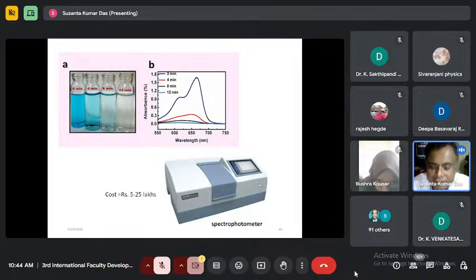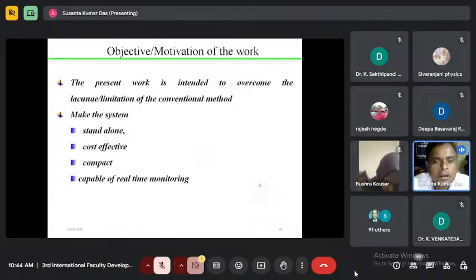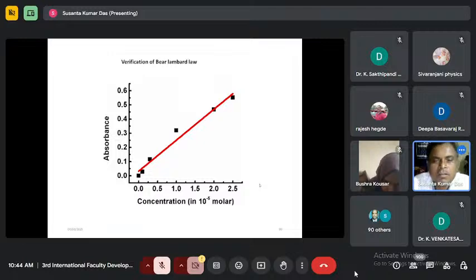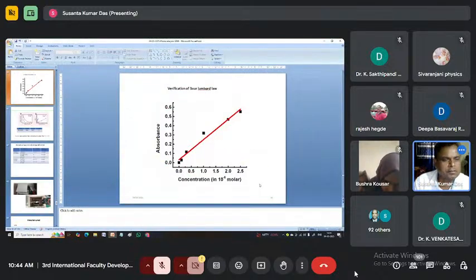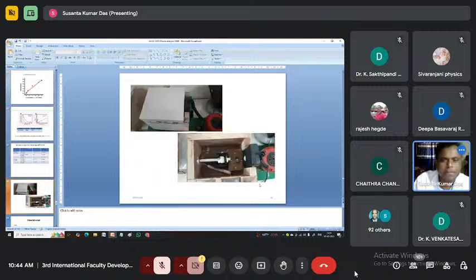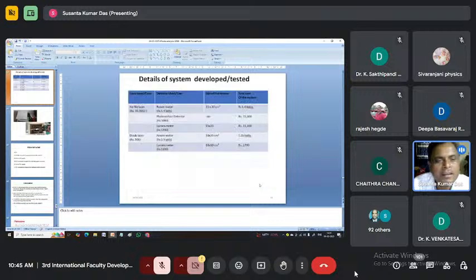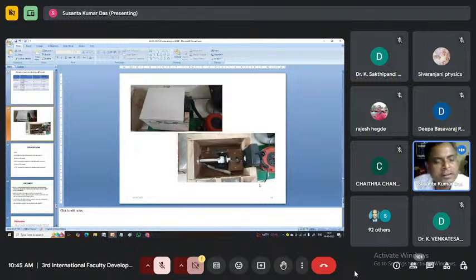So I tried a very simple setup, and the setup I'll show you. This is the setup actually. On one side I placed a lux meter, on the other side the laser source, and in the middle I kept the sample. It was a very simple setup, and I can easily measure the transmittance, and from the transmittance I can easily find the absorbance, which is what I did. I verified with the conventional one also, and found it gives a similar result.